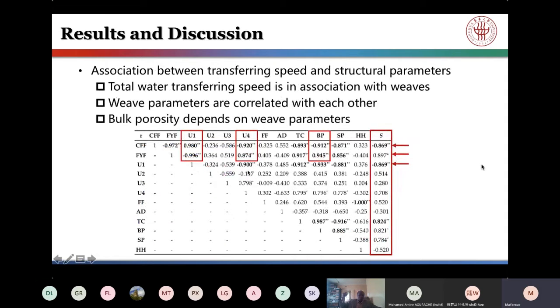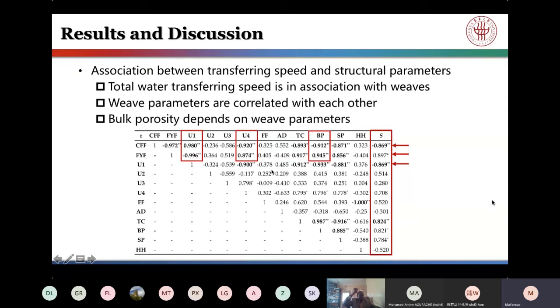What's more, in the study, we also use correlation analysis to evaluate the strength of the association between total water transferring speed and the investigated variables. And their results are listed in this table. Among all the variables, we can see that these three variables, that's FYF, which is floating yarn factor, had the largest correlation, followed by CFF and proportion of unit 1. This means that total water transfer speed has a strong association with the weave.